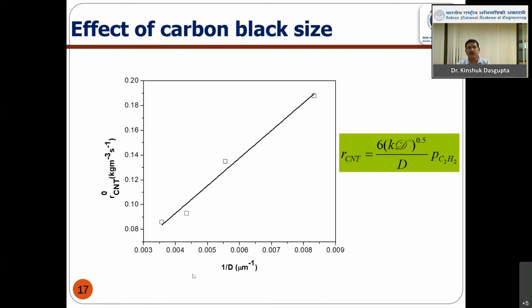So if we plot 1 by d, where d means the diameter of the agglomerate, against the rate of carbon nanotube formation, we get a straight line, from which we can derive an equation to describe the process, the reaction rate at the high temperature regime.